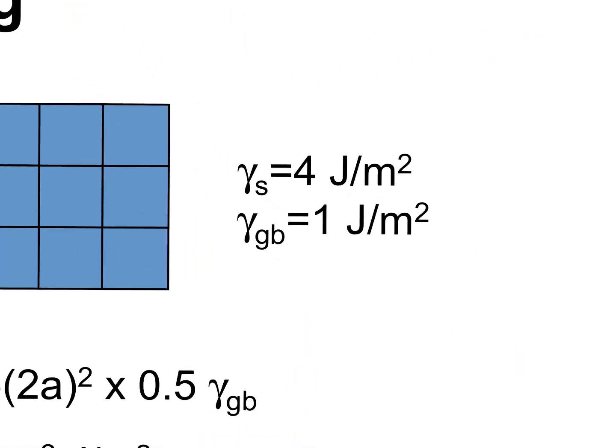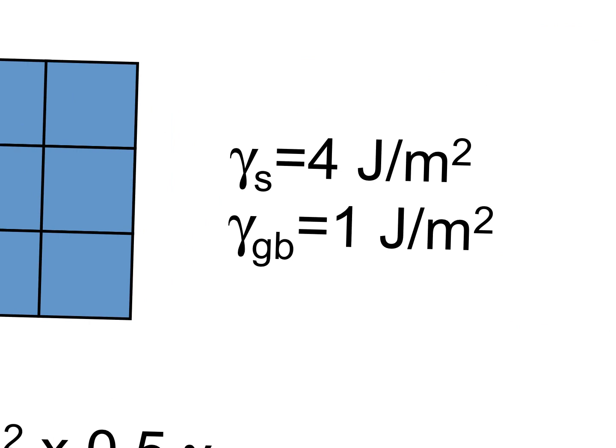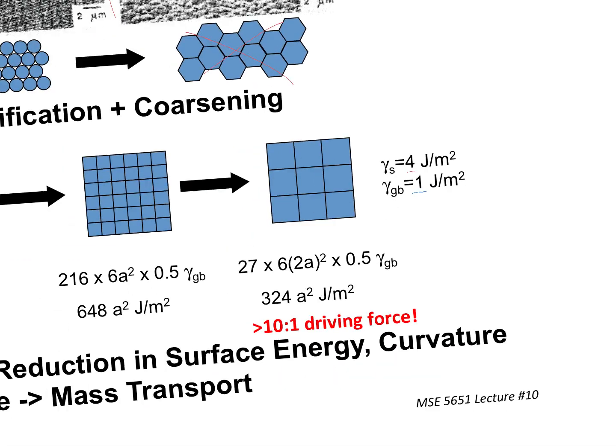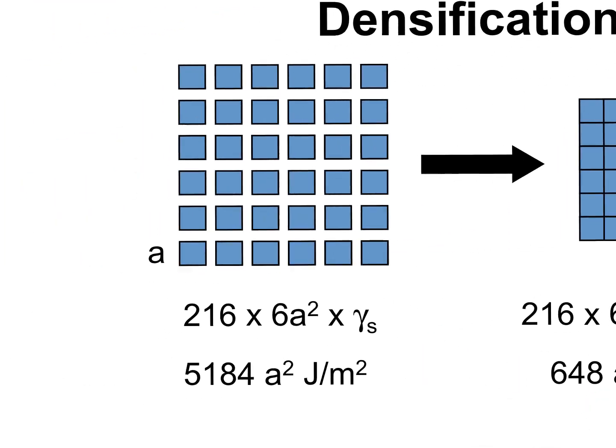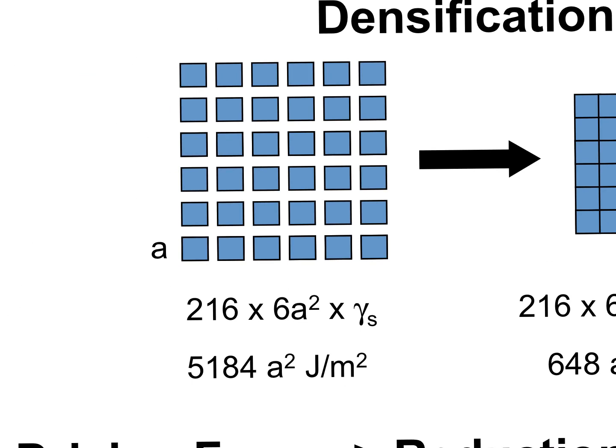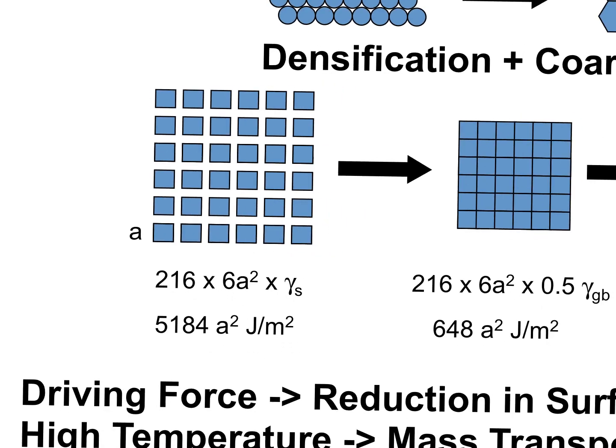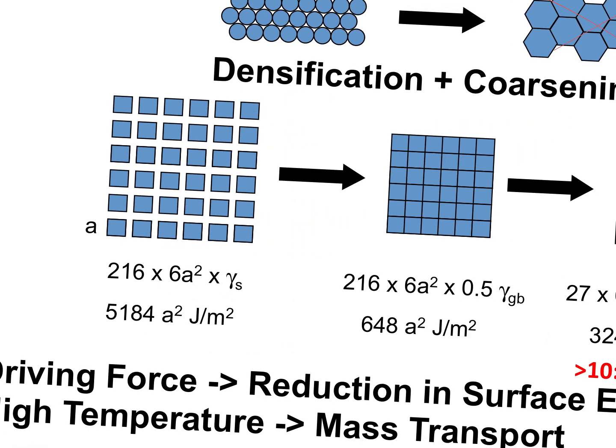And for this particular experiment, what we're doing is we're defining gamma for the surface itself as being 4 joules per square meter, and for, as you'll see, the grain boundaries, 1 joule per square meter, all right? So we're throwing in some numbers, and these are kind of realistic in terms of how things scale in real processes. And so we start out with this array of cubes, and we have gamma sub s, 4 joules per square meter, is the driving force for this 6 by 6 by 6 array. And if we look at the math for all this in terms of a squared, it's 5,184 joules per square meter. And that's just sitting there floating in space, by the way, they're not touching each other.